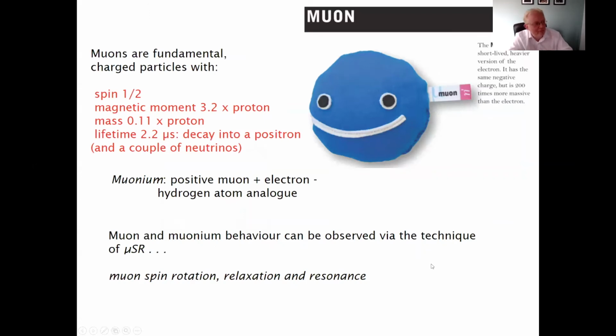And muons. So a slight aside, we make positive muons, and these are fundamental particles with charge, and they behave like large versions of their equivalent fundamental particle. And what we do is you put a proton beam through a carbon target and you make a positive muon, and the muon will embed within a material, and it will behave much like the material that its position it's occupying. So you make this positively charged muon into a lithium battery material, and it behaves much like the lithium that you're interested in motion. And after a while, that muon will decay and it will produce a positron, and that positron is then detected by our detectors.